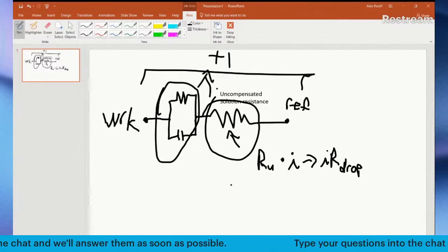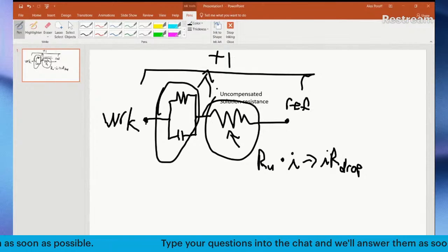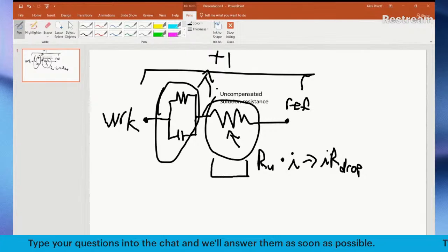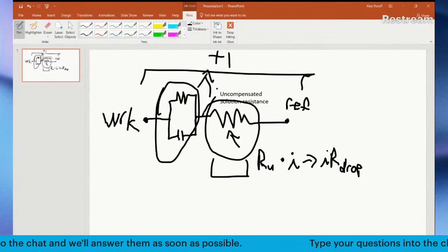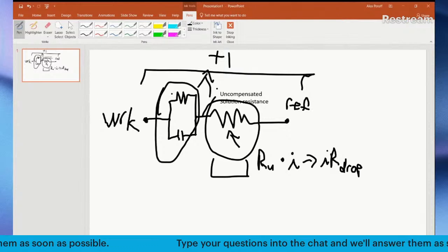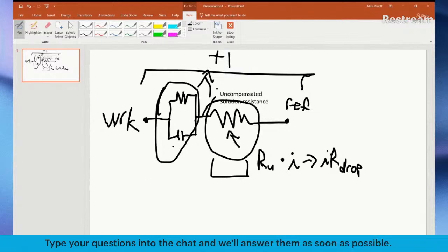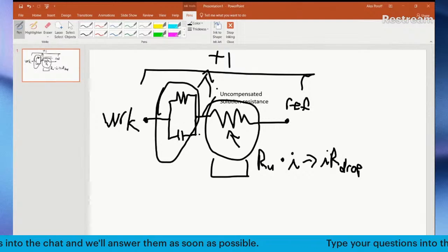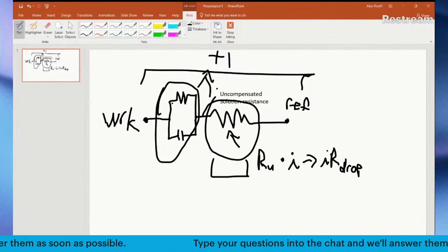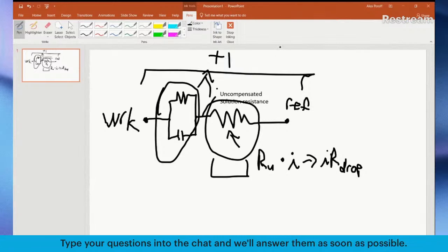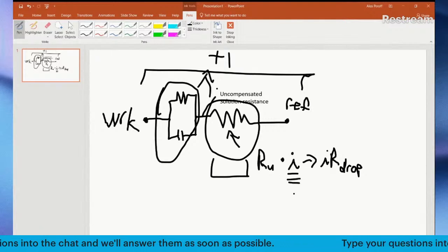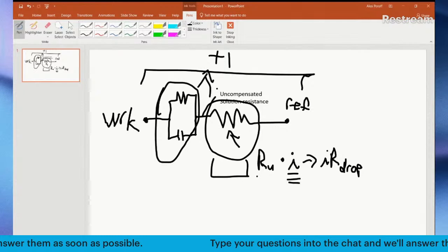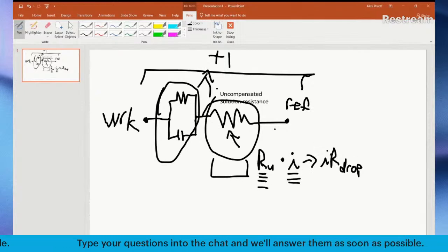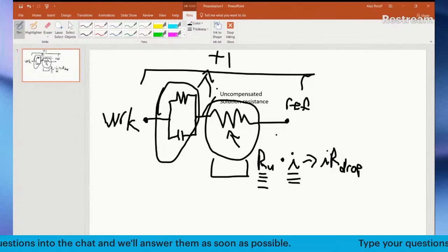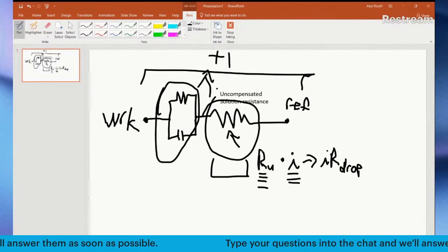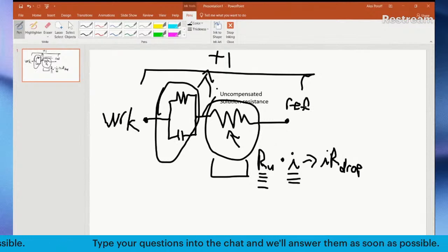And if you are doing electrocatalysis and you are studying this process here, this becomes very problematic because you think you're applying plus 1 volt to your electrocatalytic system, but really you're applying less than 1 volt. And this leads to a lot of inaccuracies. So especially in electrocatalysis, when you have a lot of current, so when this gets big, that's a problem. If you have a large area and there's a lot of solution resistance, this becomes a problem. And so you can see huge changes. I ran this kind of demonstration at the CV bootcamp I did last week.